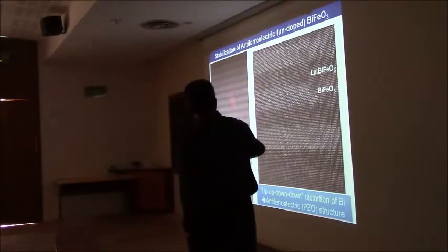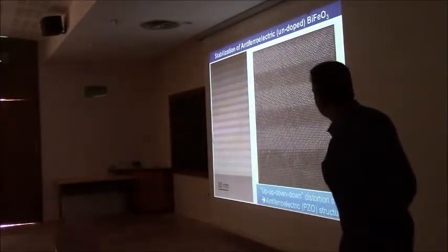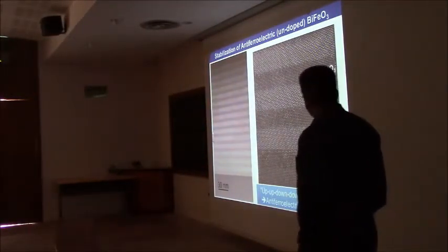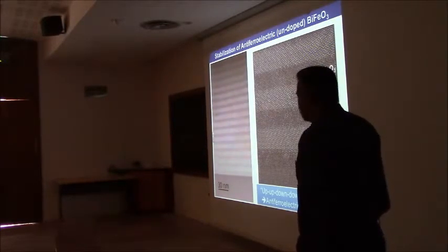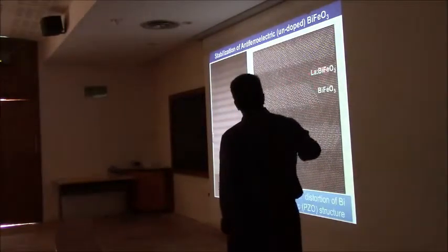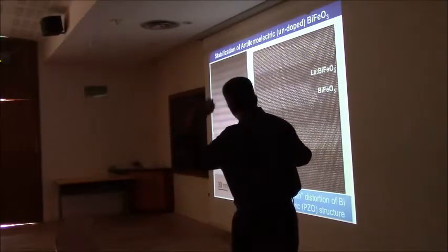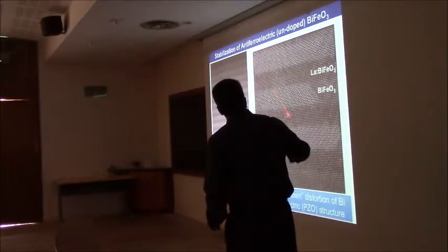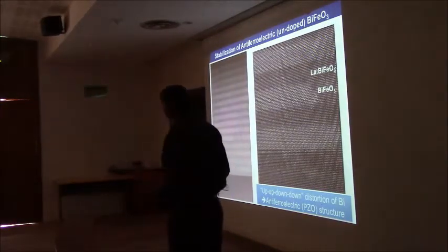And when we looked at these superlattices, these were grown in Darrell Schlom's lab by MBE, perhaps the best that we can grow so far, what we saw was something unexpected. We were expecting domain formation. Instead, the lanthanum doped bismuth ferrite did nothing. And by the way, there's no chemical interdiffusion, it's all pretty okay. The bismuth ferrite went into an antiferroelectric phase, which we did not expect at all.